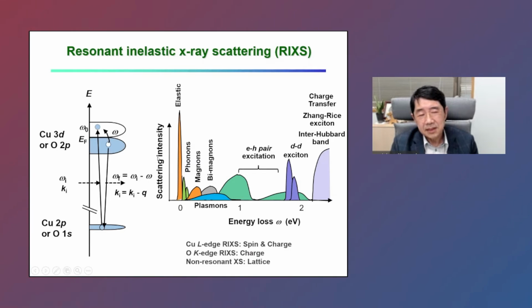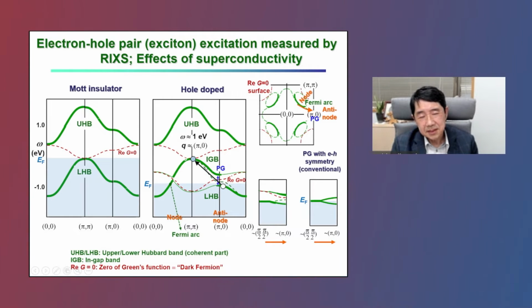And using RIXS, resonant inelastic X-ray scattering, one can measure electron-hole pair excitation. So in this view graph, excitation of an electron from here to here creates an electron-hole pair with a finite momentum and finite energy. So this is quite different from the electron-hole symmetric situation. Below superconducting Tc, the superconducting gap opens. So above and below Tc, the electronic structure in this region is quite different, and the pseudogap and superconducting gap compete, unlike the conventional electron-hole symmetric pseudogap.